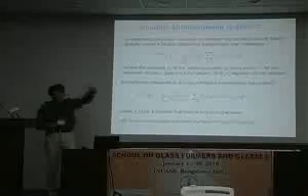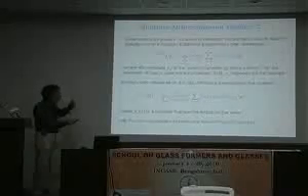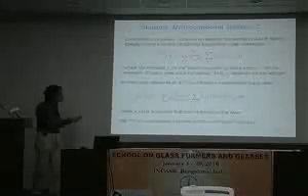However, what you do in reality, so you have a multi-component sample, you put it in your sample holder, you do your scattering experiment. What you are measuring, this is exact, is a linear combination of these partial structure factors. So here alpha and beta run from 1 to nu. So you have nu square terms here because you have nu square partial structure factors. And here you have a funny prefactor that comes from the normalization. So that's what is accessible in a neutron scattering experiment.